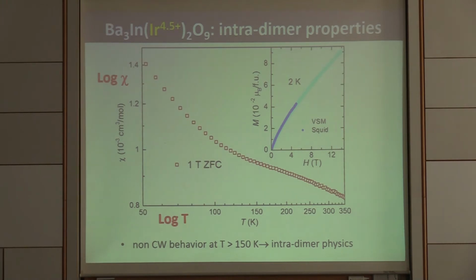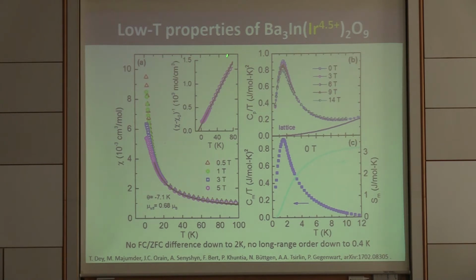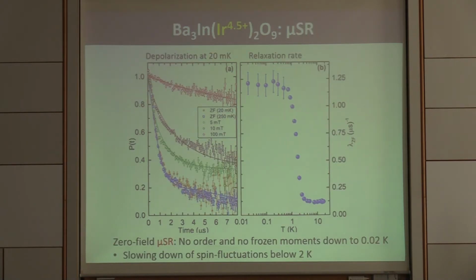In the bulk magnetic susceptibility, here I show you log chi versus log T, we see some nonlinear dependence, a shoulder near 150 Kelvin, which is probably related to the intradimer physics. But then at low temperatures, we see a Curie-Weiss-like behavior below 100 Kelvin with an antiferromagnetic Weiss temperature of about minus 10 Kelvin. There is no signature of order down to 0.4 Kelvin, and there is no field-cooled, zero-field-cooled difference seen in the magnetization. We then looked at muon spin relaxation data down to 20 millikelvin, and we see that there is no indication of long-range order down to that temperature, and also no frozen moments. We see that the relaxation rate from the muon experiment increases and then saturates below a temperature of 2 Kelvin.